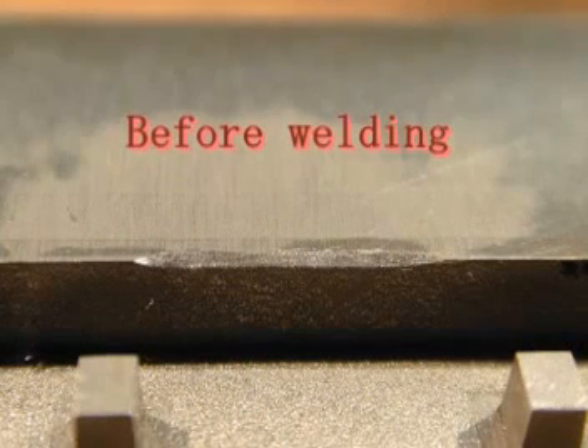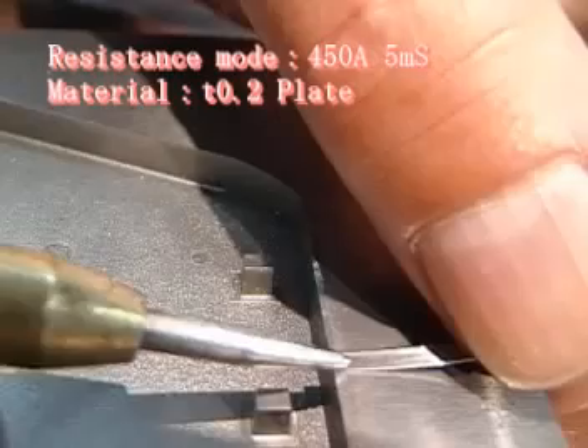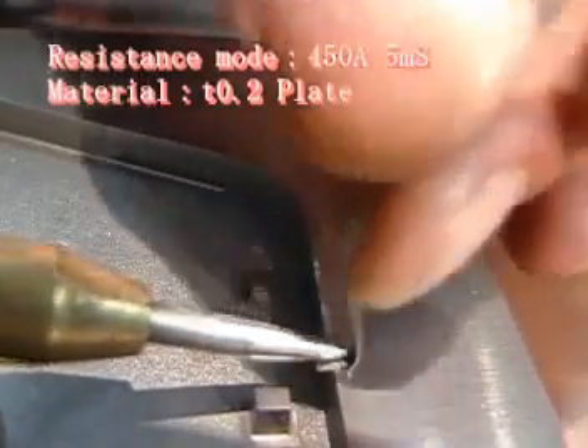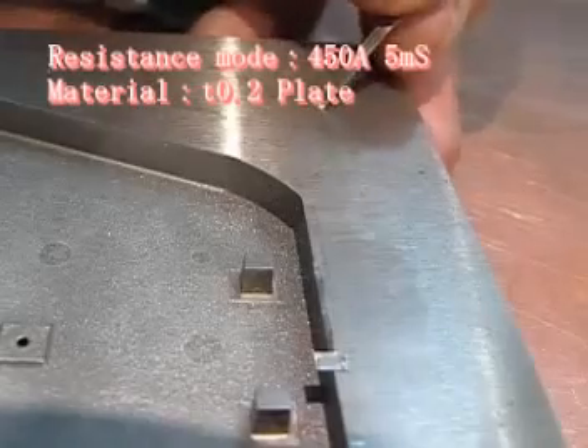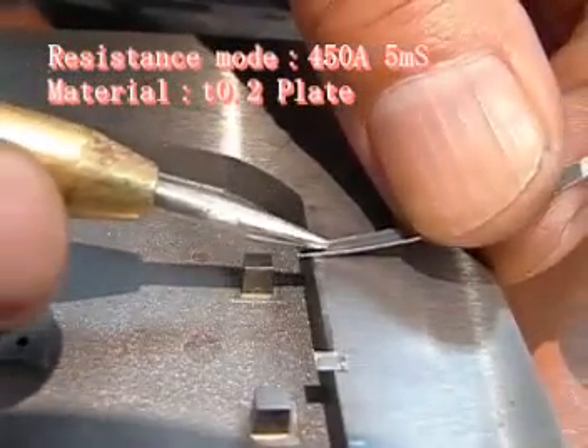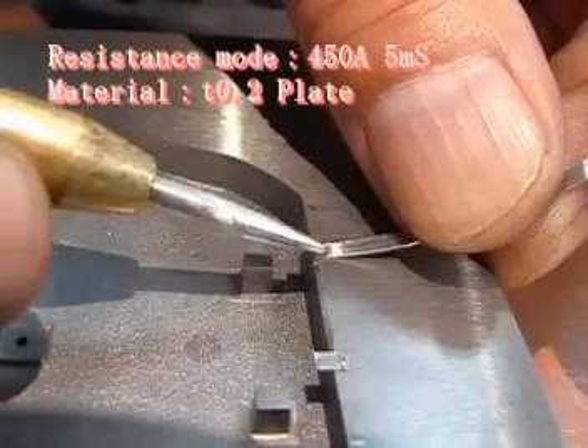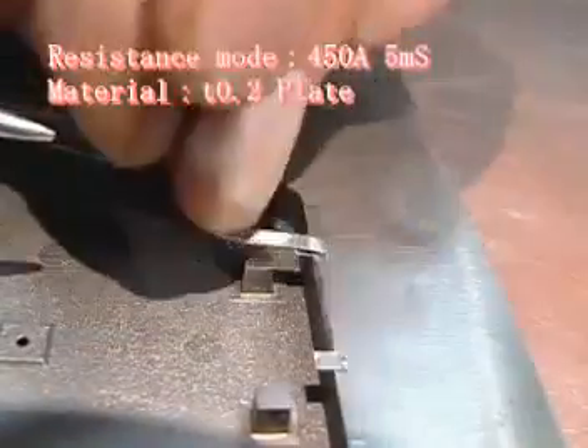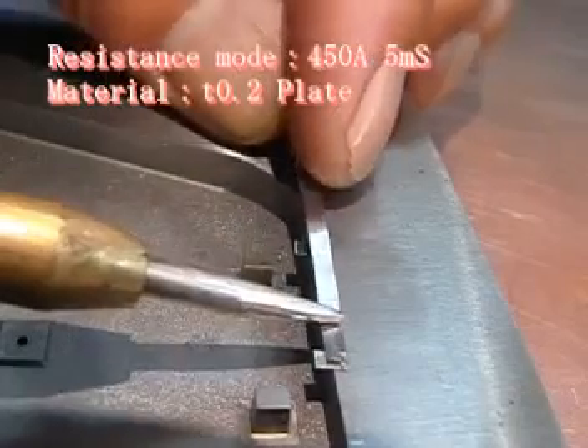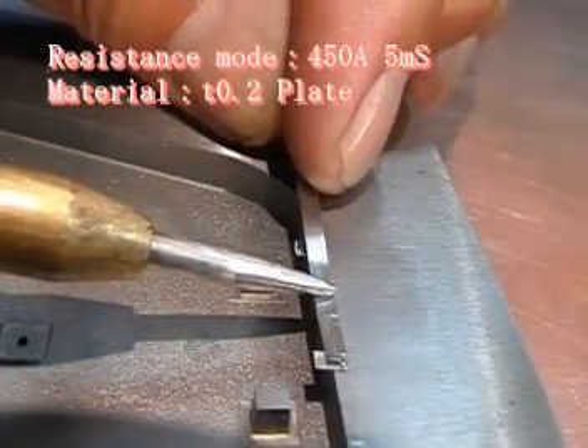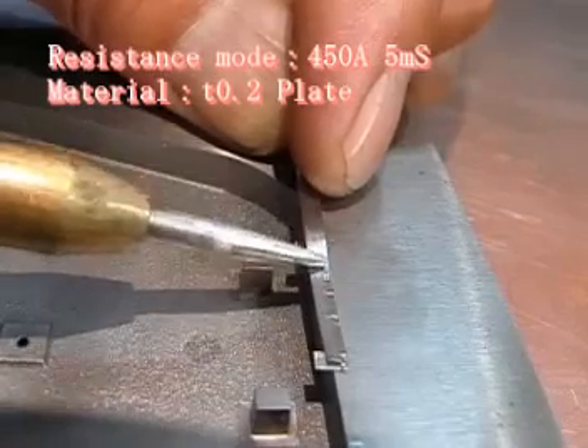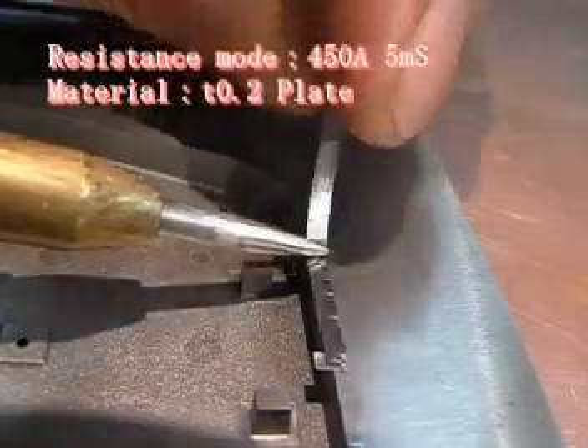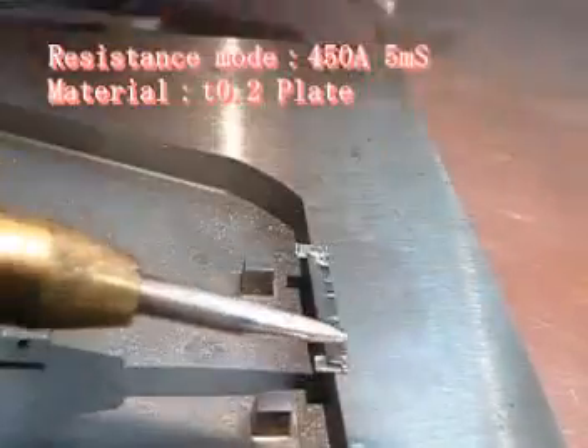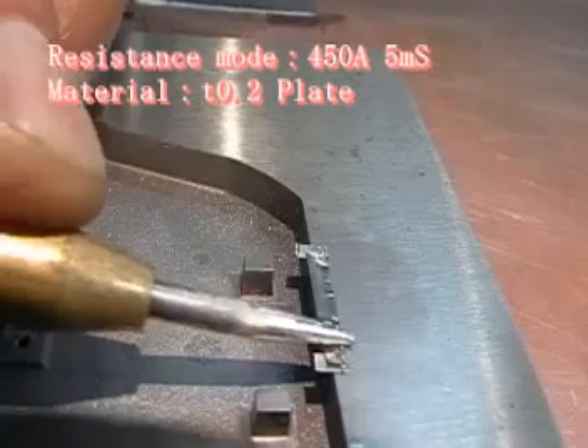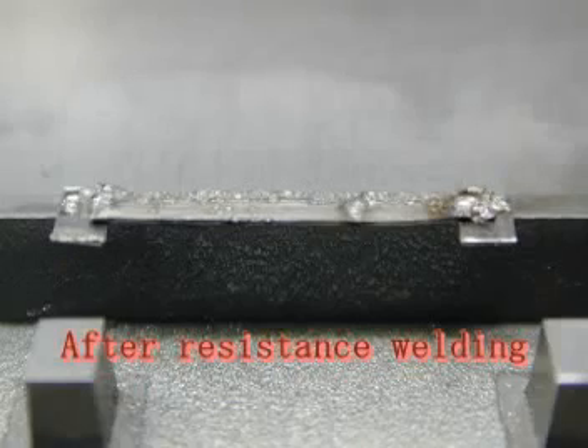I will show you how to repair parting lines using plate materials. First, join welding materials temporarily by using the resistance welding mode. Place welding materials in a lengthwise direction on both sides to avoid shrinkage on the edge. Then, place materials so that half of their lengths stick out of the edge and fix them temporarily. It's easier if you fix 4 or 5 places first to keep the welding materials aligned, and then fix them all together. Fix them securely in this way.